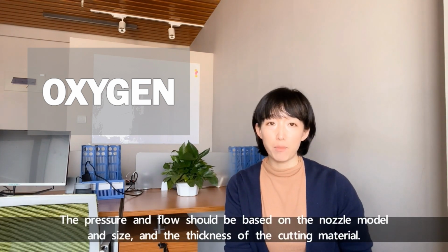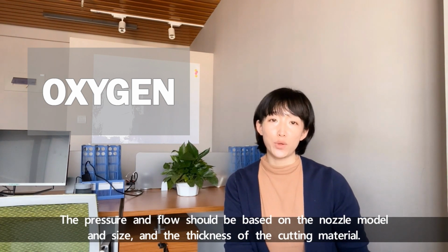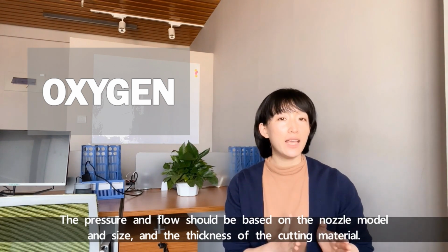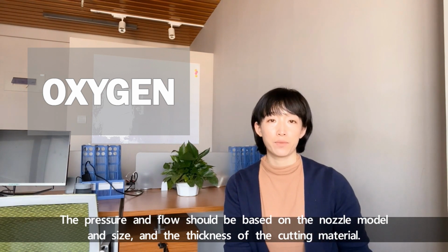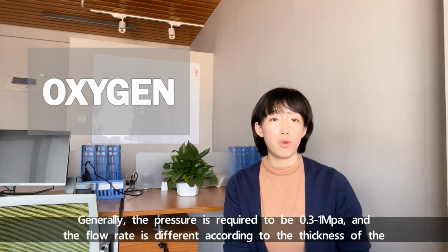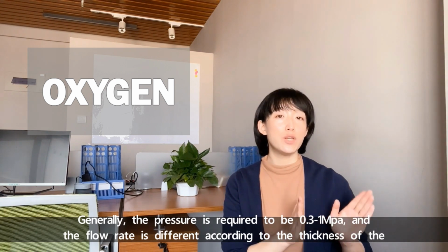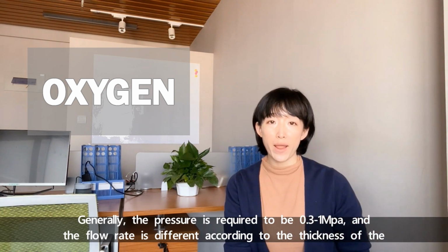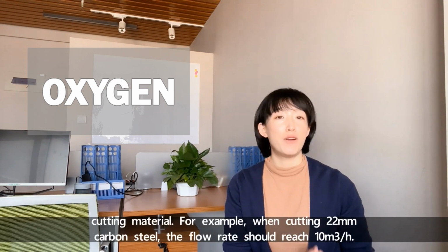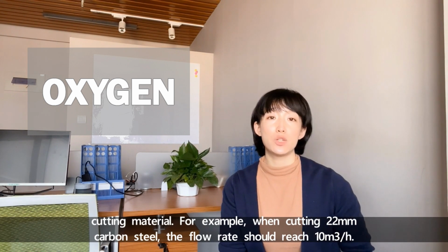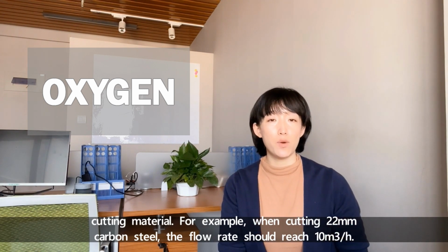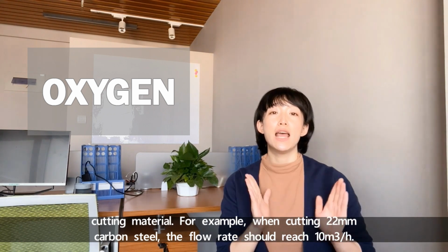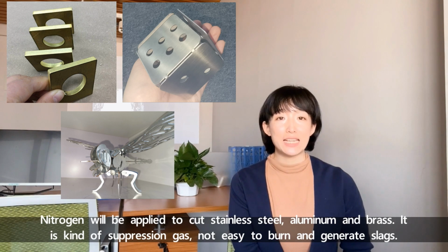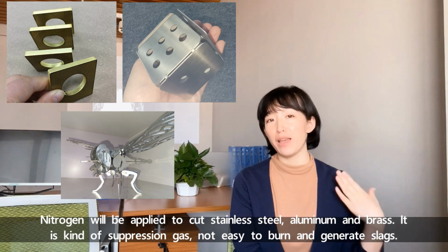The pressure and the flow should be based on the nozzle model and size and the thickness of the cutting material. Generally, the pressure is required to be 0.3 to 1, and the flow rate is different according to the thickness of the cutting material. For example, when we need to cut 22 mm carbon steel, the flow rate should reach 10 cubic meters per hour.